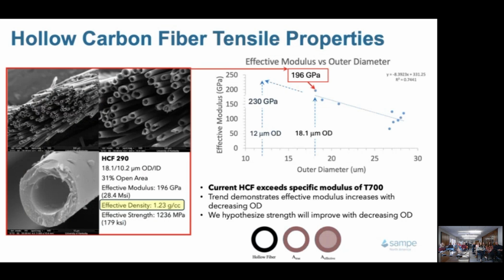If we look at the effective modulus we've measured, we're landing around 196 gigapascal with our 18 micron outer diameter hollow carbon fiber. When we calculate that, we're using this effective diameter, meaning in the cross-sectional area we're including the hole, which is fair because the composite doesn't know there's a hole there. That brings our numbers down. But these results trend to suggest we'd arrive at 230 if we could produce a fiber that was 12 micron OD. That's where we're going.